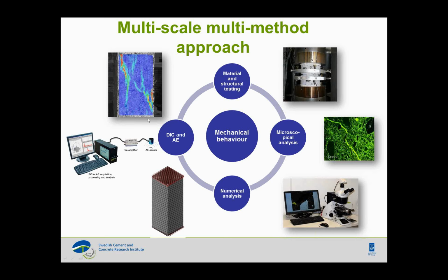We used digital image correlation and acoustic imaging to look at the strain localization on the surface of these piles where they were tested, and also we used acoustic imaging to see where we have the highest fracture activity to better understand the failure mechanisms. And then we also used microscopical analysis to better quantify the impact of sulphate attack in terms of how much expansion we have. So we counted the cracks, we calculated the crack widths in a representative volume, and from there we calculated how much expansion we have had in this specific case.